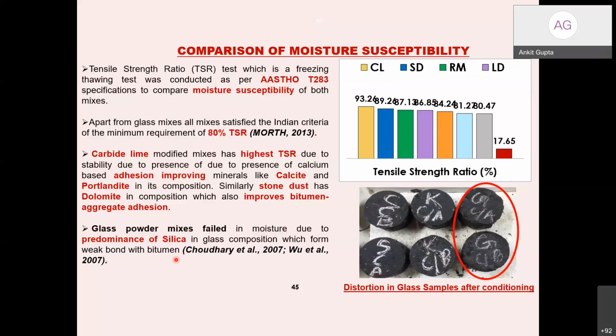Except this glass powder, all these fillers are giving good or satisfactory results with respect to moisture susceptibility also. We did some experiments with the glass powder, because we cannot just leave it since it is not able to sustain one of the results. So we did a modification of the glass powder and made some composite fillers. We mixed some percent of the carbide lime in the glass powder dust, and checked its performance, and the composite filler was again giving good results.